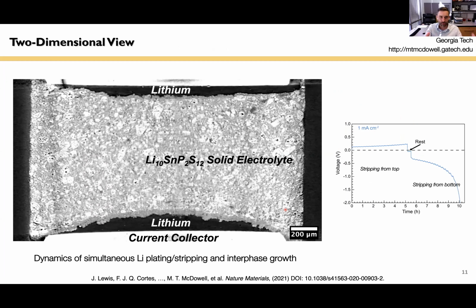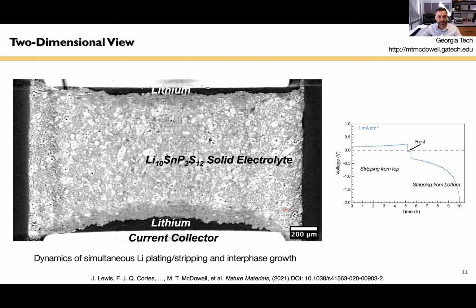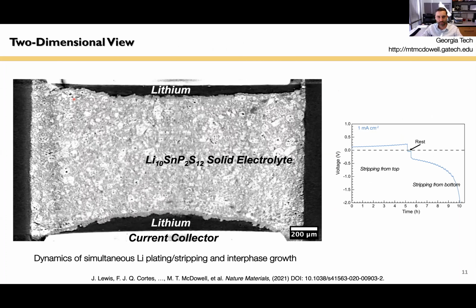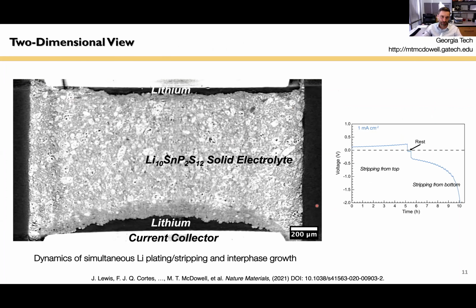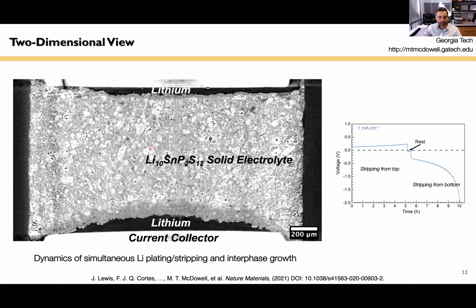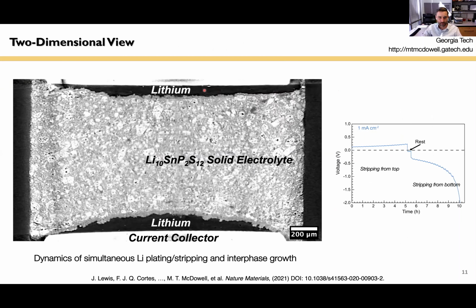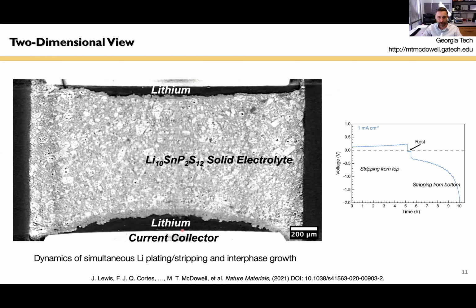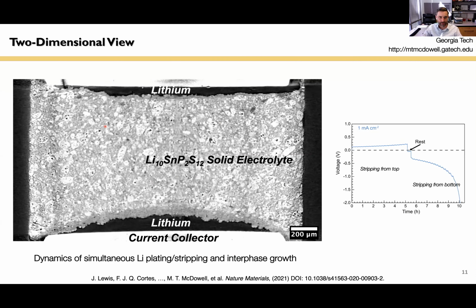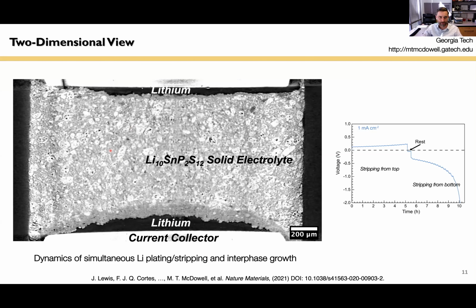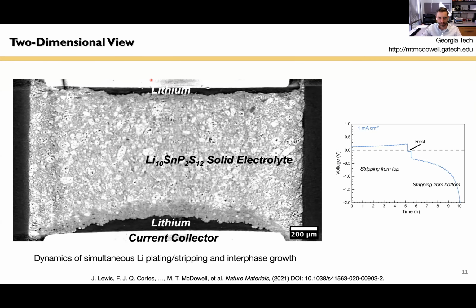So this is not a complete 3D scan now. This is only a single 2D slice through the cross-section of our cell. It's more than one slice because this is a video. I hope you can see the video. So it's a time series of slices, but a single slice across time. And what you see here is the stacked materials in the cell. We have the darker regions up here and down below, which are the lithium metal electrodes. In the middle, the thick region that has kind of a granulated contrast, this is our solid electrolyte material. And then at the top and the bottom, you can see this very white region. These are the steel pistons that are the current collectors.